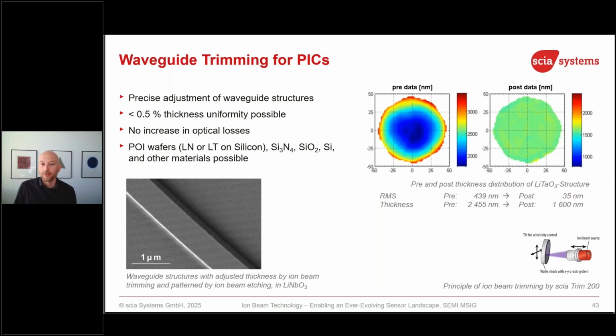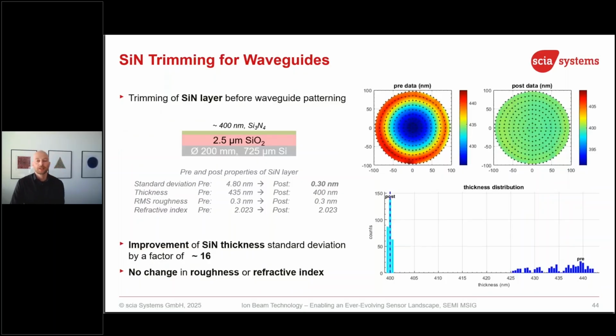Anyway, ion beam trimming is used for the thickness correction, and not only on lithium niobate, also silicon nitride. Silicon nitride is also a very common material for photonic integrated circuits. Structuring is done by RIE, no need for ion beam, but uniformity is challenging. Maybe we have a look at those numbers here. You see the thickness before we apply the trimming process is around 400 nanometer. 4 or 5 nanometer standard deviation means 1% non-uniformity. It's not too bad, right? But we don't want 1%, because this still means a couple of nanometers plus minus. We need plus minus 1 nanometer non-uniformity. And the only way to get it is to apply ion beam trimming.